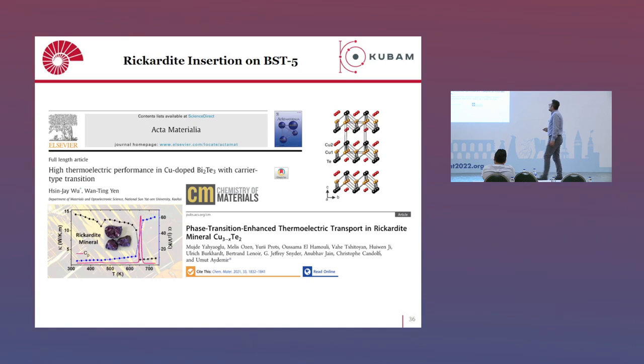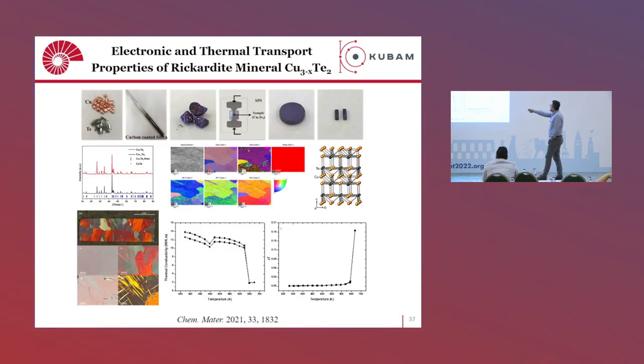Now we saw in the literature that copper is a very good dopant to optimize the thermoelectric properties of bismuth telluride. And while we saw this paper, we were making another research on copper telluride. This copper telluride is a synthetic rickardite mineral. It shows nice properties. You can straightforwardly make it with solid state synthesis. You see that this is a very good crystalline, purple-like material. So you can make it with this method. And the crystal structure is also layered-like. It doesn't show here, but it is a layered-like structure.